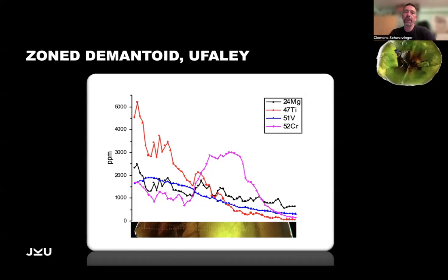and you're a little bit trained in chemistry and physics, you can understand why people in Russia throw the demantoid garnets into an oven, because the titanium and iron complex breaks up, so the brown becomes colorless, and you see the yellowish to green coming in this position. So many of the demantoids from Russia that you have in your jewelry have been heated. The problem is you cannot detect it because it's very low temperature and there is no change in any composition.